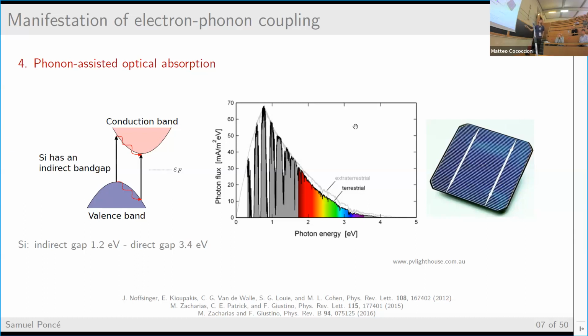And this is why silicon is used for photovoltaics, and it's very good in that way. Notice that in that particular case, because you need both a photon and a phonon at the same time, typically you need quite a thick layer of silicon in order to be able to absorb.